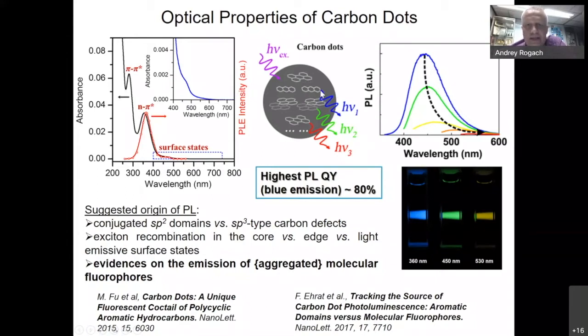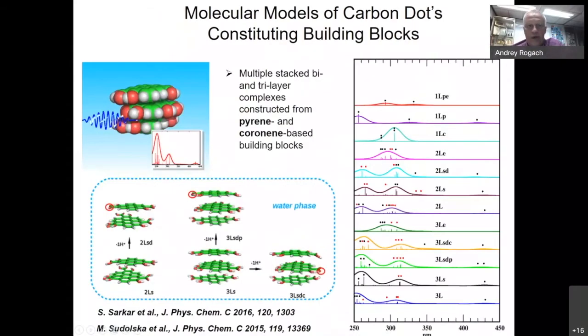So you can see that they have so-called conjugated sp2 domains, which can be monolayers or two layers on top of each other, and there may be different numbers of benzene rings here. And all these domains actually remind us of something we know from organic chemistry. I jump to my next slide here, and we call these building blocks pyrene or coronene molecules, right? Essentially, we can think about carbon dots as built up from multiple stacked two- or three-layer complexes, which are constructed from pyrene or coronene-based building blocks.